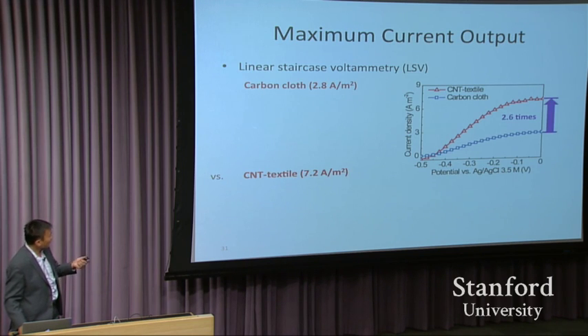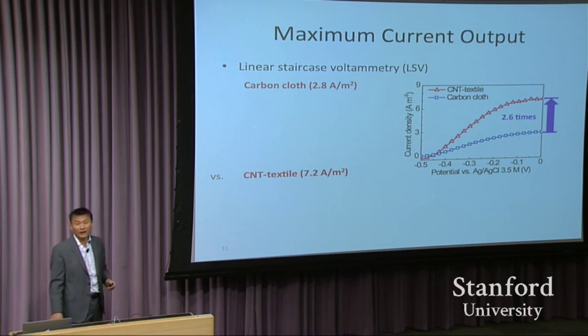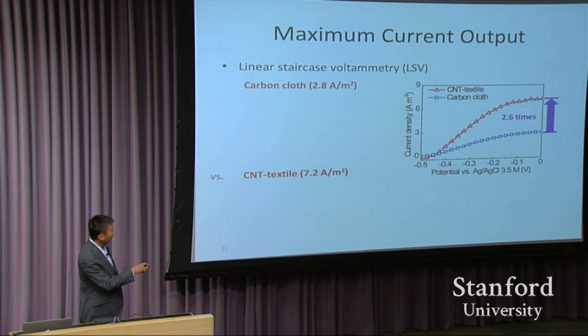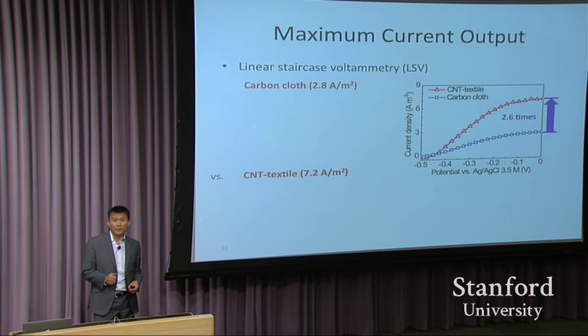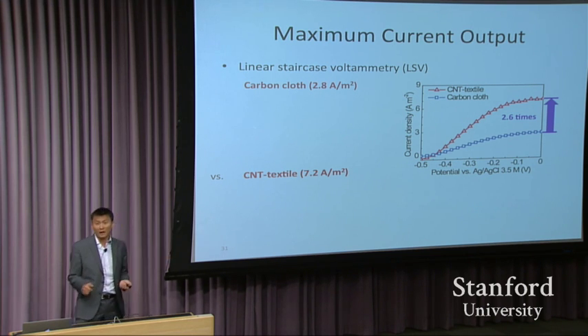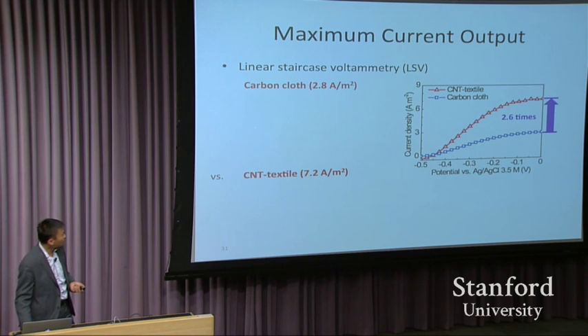So it turned out to be, we have the power output, we measure the current versus potential. The red curve is our CNT textile, carbon nanotube textile. We can have 2.6 times more current than the one of carbon cloth. That was considered the state of the art, that's carbon cloth. So we have a lot more energy collected compared to the past electrode materials.